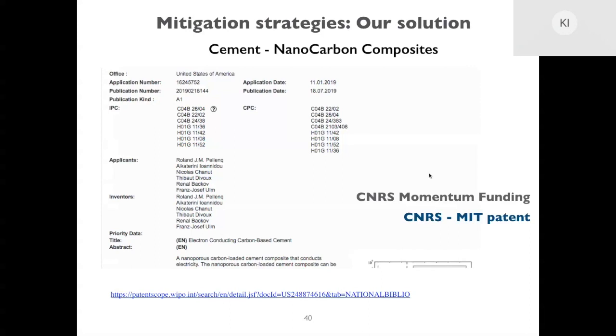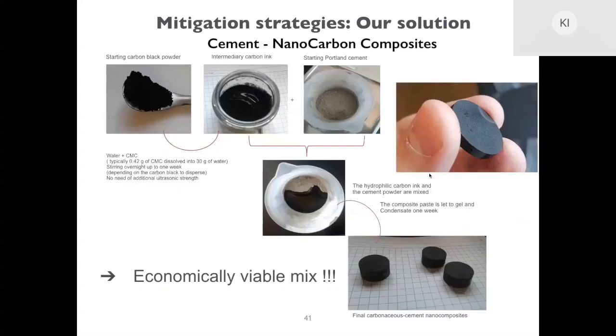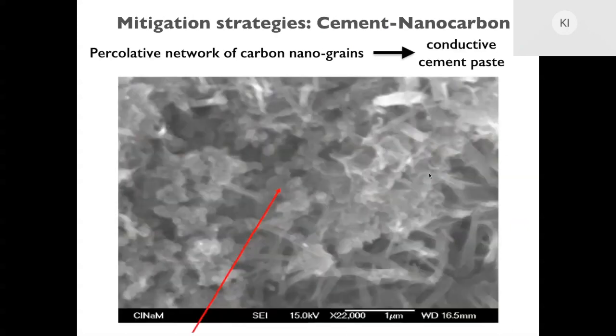I'm going to explain to you very briefly how we make this material and what we can gain for durability issues. So the idea is very simple. Basically, we're mixing cement with nanocarbon particles, two materials that are both very cheap. So overall, you have a black cement, which is very affordable, and this material has several properties that all come from the fact that we have a percolative network of carbon nanograins inside the cement. The first thing is that the cement paste becomes conductive. Carbon is a conductive phase, and as long as it percolates the material, we have a conductive cement paste.